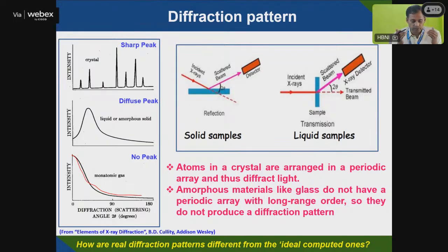But in the case of a liquid, you will get a liquid amorphous pattern. If there is short range ordering, because of it you will get humps at around 2 theta of 27, 28 degrees, or 25 to 27 here. You will get a broad peak.